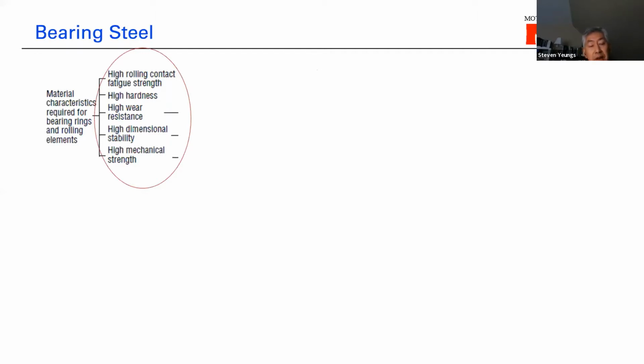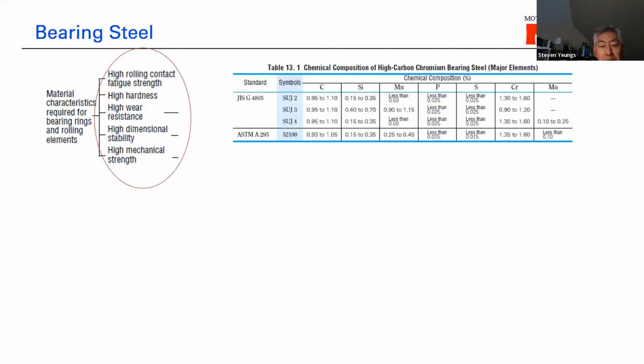The bearing steel should have very high hardness. Today's hardness values are about 58 to 62 Rockwell C as the standard range for most bearings. High wear resistance, high dimensional stability. Normal bearings could be used up to 120 C, but some bearings are made up to 200 degrees Celsius, and then high mechanical strength. Typically, the most common is the through hardened steel that people might hear about from time to time. Through hardened steel indicates that through the cross section the hardness remains the same throughout.